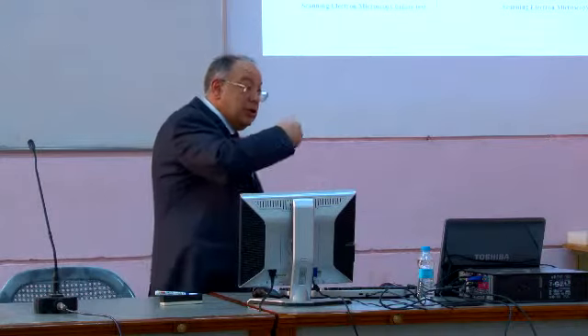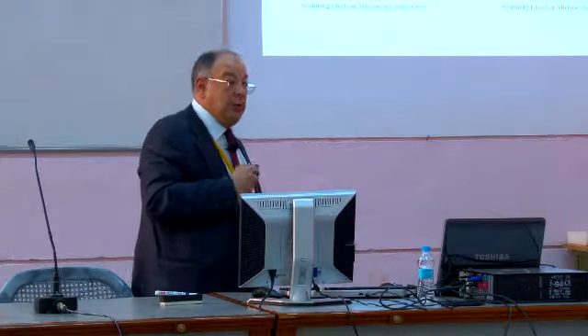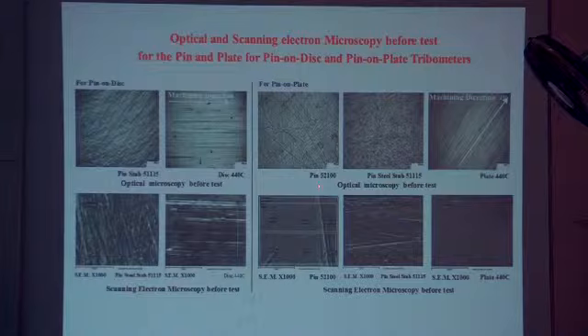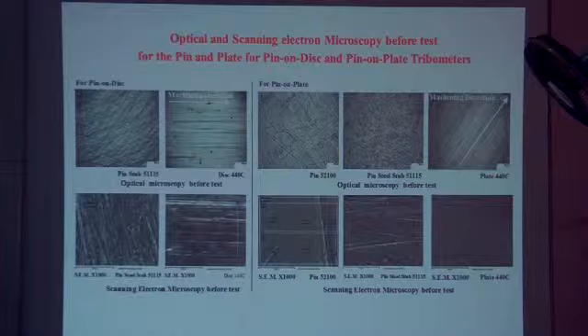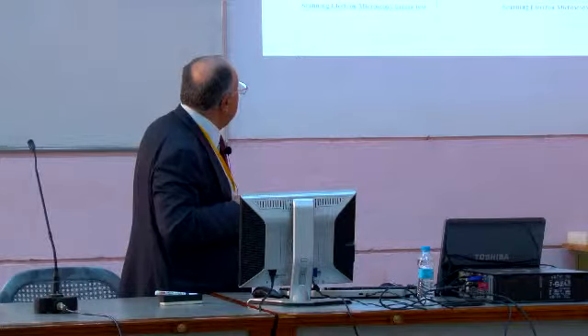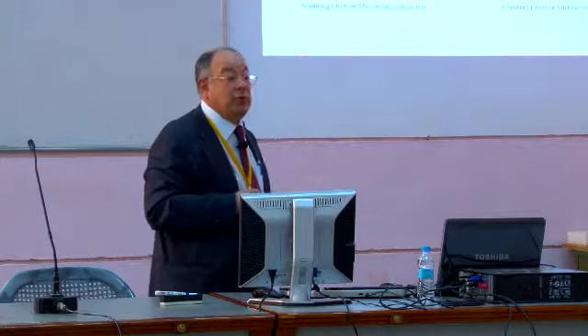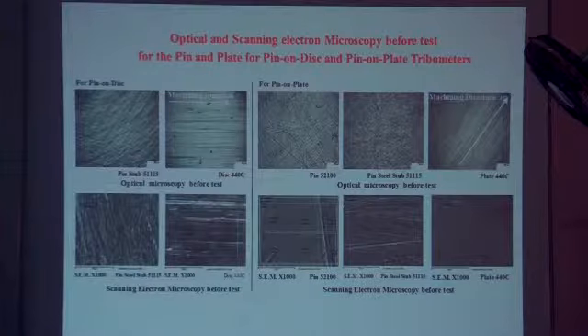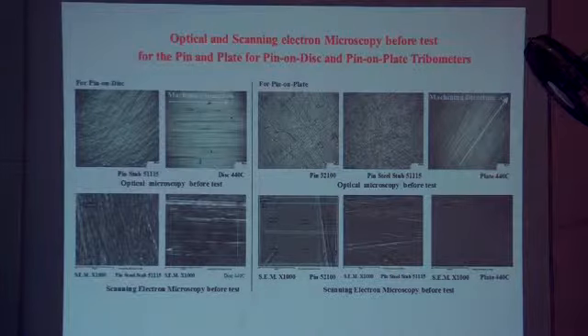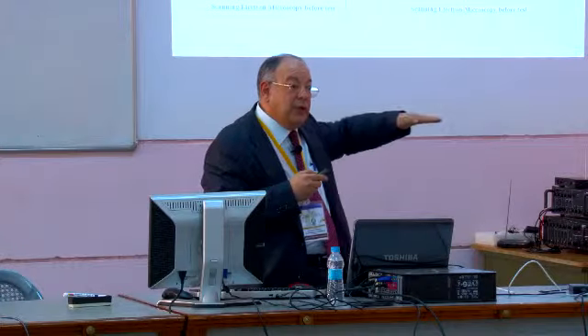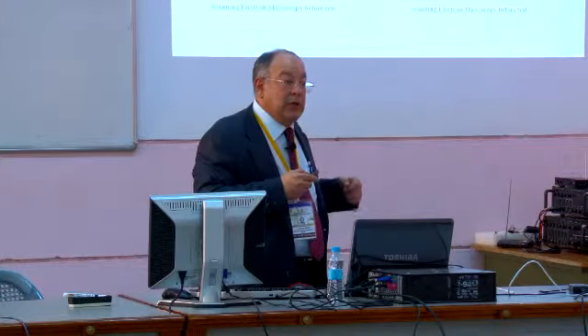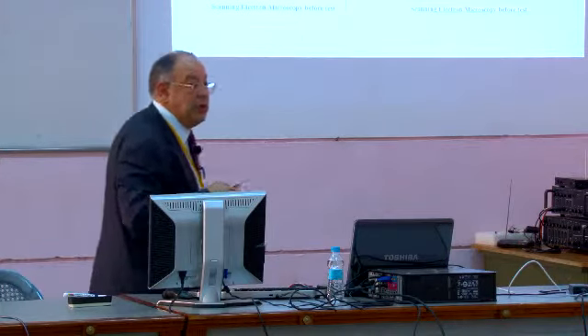The slide I showed you, we obtained the layers with the pin material 52100. Yes, we obtained it, but it's a bit harder than on 51,115, where we obtained more layer on the surface. Because of the surface degradation, it's very appropriate to adapt the surface to get a slightly nice, flat surface where the additives chemically react.